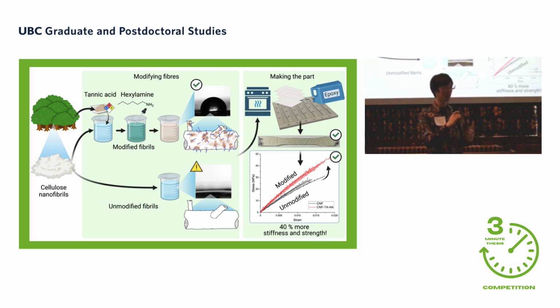What this means is water, when it tries to touch the surface of the cellulose nanofibrils, is blocked by these amine chains. As a result, they repel water, and the contact angle of water increases dramatically. So what does this all mean for the resulting composite? My material can be dried using an oven, which is a pretty harsh drying method, chopped up and mixed with resin, and the resulting composite has a 40% increase in modulus and stiffness compared to the same quantity of the unmodified hydrophilic material.